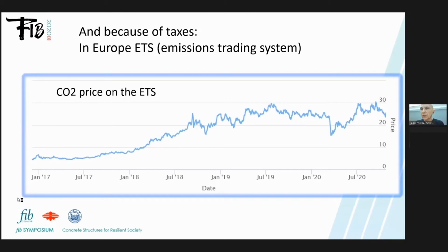Let's say the price is 50 euros per ton. For 1 ton of clinker, you emit around 800 kilograms of CO2. It means that you have to pay 40 euros per ton of clinker, which is very important. Actually, 1 ton of clinker is around 100 euros. So it means a 40% increase of the price of the clinker. So it's a very big incentive for the cement companies to reduce the CO2 emissions.